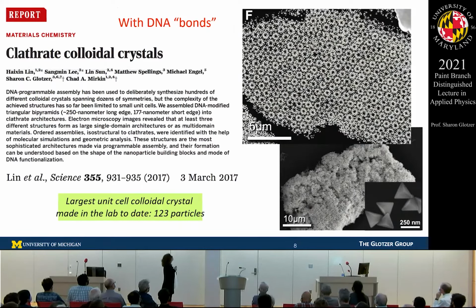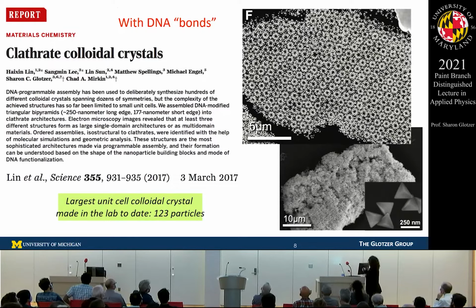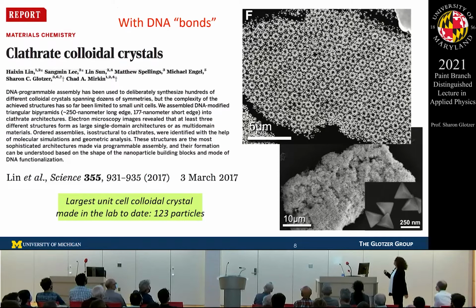This is the most complex colloidal crystal that I'm aware of that's been made so far. It also comes out of Chad Mirkin's lab. Here, each one of these little bright spots is a nanoparticle. These are what the nanoparticles look like. This is a 250 nanometer scale bar. And again, they're gold. It's hard to see from this picture, but if you were to take a tetrahedron and glue it to another tetrahedron so it's aligned and then squash it, that's what these are. That's the shape of these particles.